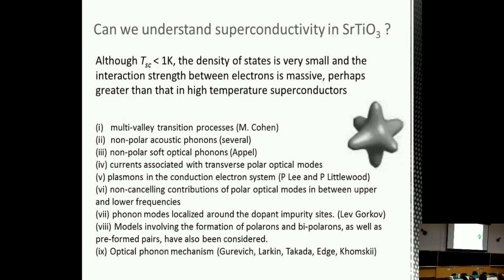And there have been many proposals over the years, starting with multi-valley transition processes. But strontium titanate, in fact, doesn't have any multi-valleys. It has one Fermi surface pocket at the zone center, as shown here. So a multi-valley kind of model for superconductivity is not effective here. And then various other cases have been tested out, such as superconductivity arising from the acoustic phonons, from non-polar soft optical phonons at the edge of the Brillouin zone, currents associated with the transverse polar optical modes, plasmons, electron plasmons, can they be pairing the electrons?